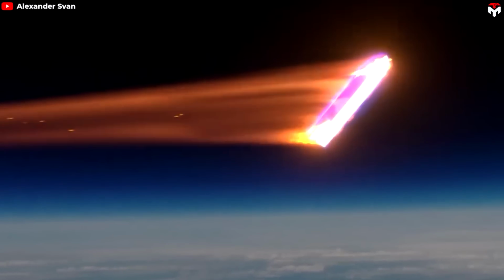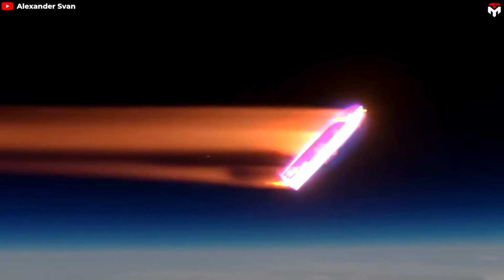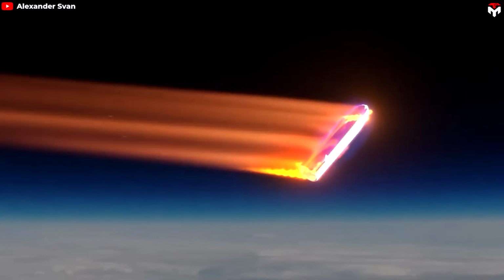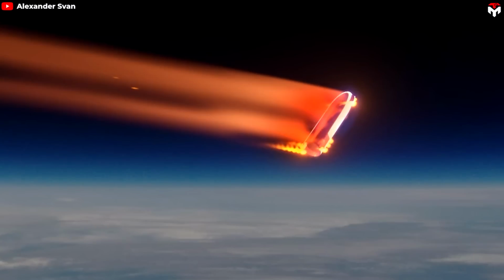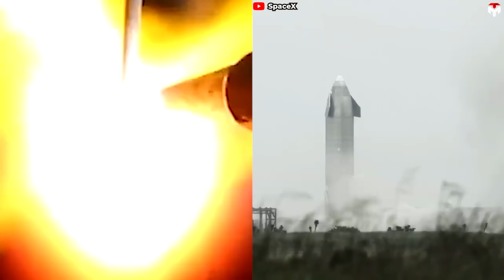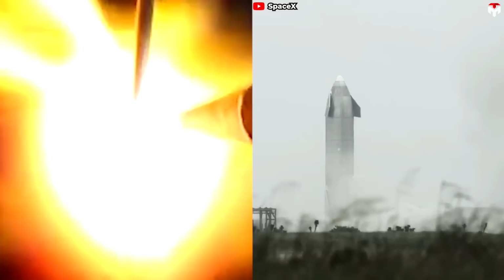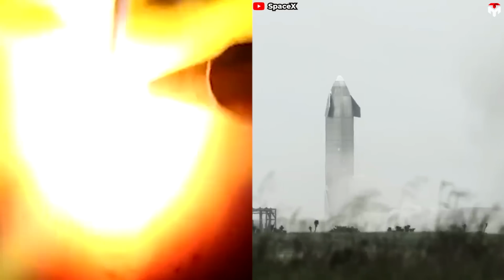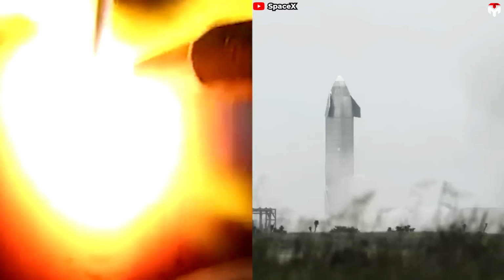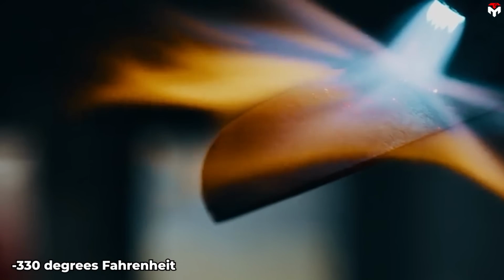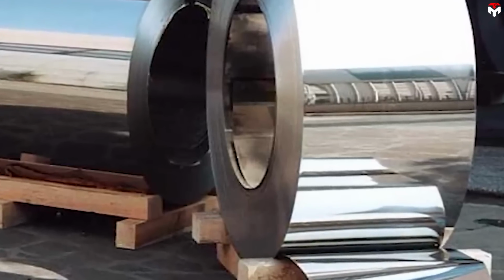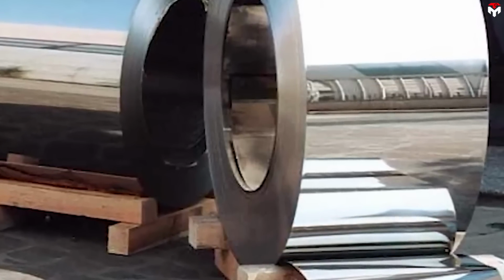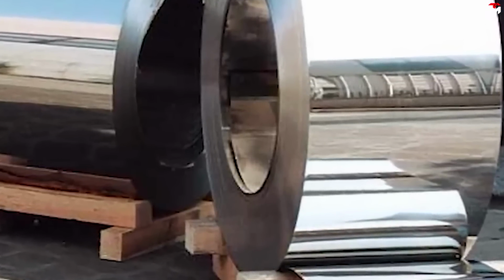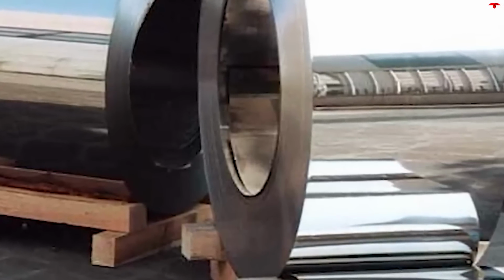We've talked about the exceptional high temperature resistance of stainless steel, but the real reason Elon Musk chose it is its durability over a wide temperature range. Most steels are very brittle at extremely low temperatures, but not stainless steel with high chrome nickel content. That actually increases in strength, and the ductility is still very high, at temperatures around minus 330 degrees Fahrenheit. Stainless steel retains a ductility of 12 to 18%, which is very high compared to most other types of steel. Very ductile, very tough, no fracture issue.